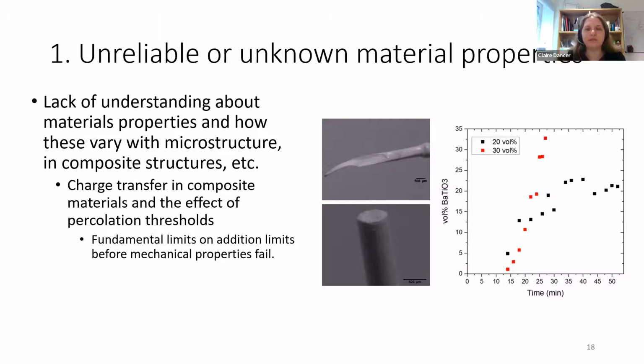But in practice, what we find with that is that there's a really strong limit, for example, to how much ceramic powder you can put into a polymer and still make it into a printable filament or an extrudable sheet of material. And we found different values for different materials. It's not a universal law. It seems to be about 30 volume% for most things, but you can push it higher. We have pushed it higher. We've also found it come out lower, depending on what degree of mixing we've had. And it can really quite radically change the material. This is some tensile tests on some 3D printer filament that we were making with the barium titanate particles inside it. You've got a stretchy, plasticky kind of structure until suddenly you don't, and you have a brittle one, which you then can't print with because it's too brittle to feed through the printer. So this can make a really quite big effect on what we see.